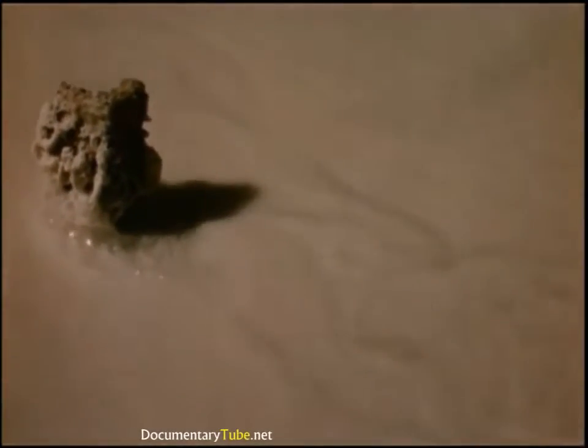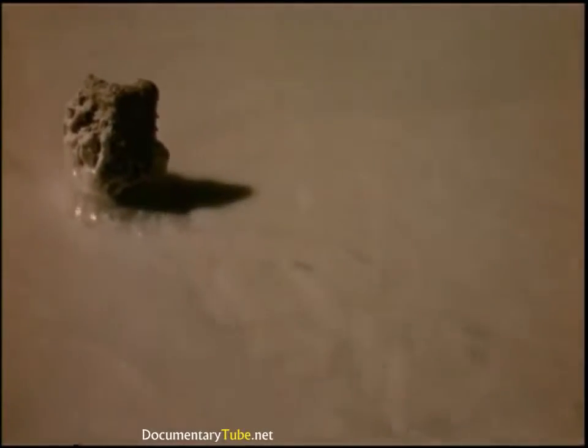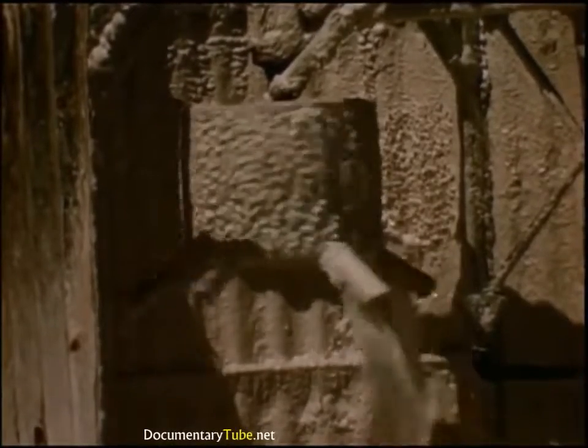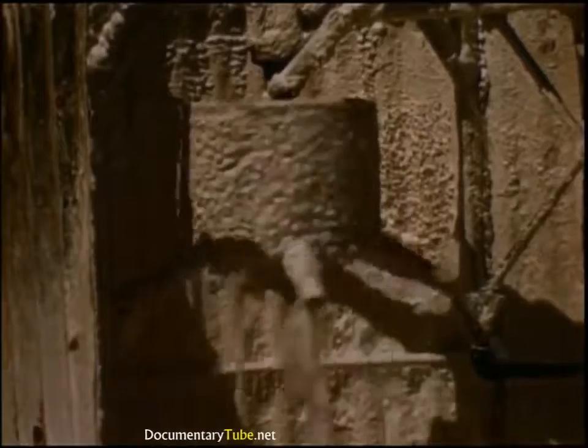Fine grains react more rapidly than the coarser ones, which settle to the bottom, where they are drawn off and recirculated with fresh slurry. A portion of the settled sludge is diluted with seawater and then passes through a rake classifier. In this way, heavy, unreactive impurities are rejected, while light magnesia and still active lime are returned. Rigid control of the entire process is assisted by continuous sampling of the reaction. The desired milk of magnesia is held in suspension near the surface, where it gradually moves with the current until it overflows into a sluiceway. Close control permits only fully reacted chemical and dissolved substances to flow on to the thickeners and washing tanks.